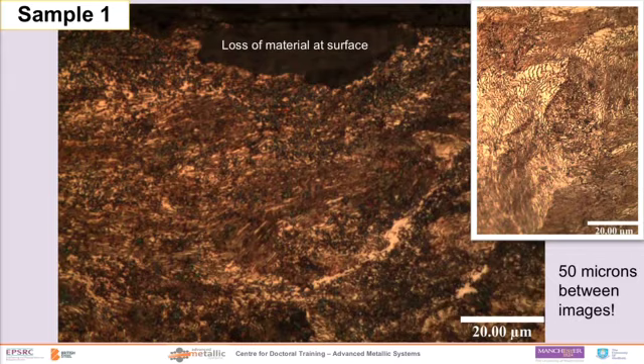So again, just to give you a bigger image of the type of martensite structure I'm typically finding at the surface of the rail. 50 microns below this image, you've then got what the structure should look like. You should be able to see the nice pearlite colonies. They should have nice clear grain boundaries, but clearly this isn't the case. And as well as being a very refined structure and a somewhat distorted structure, there's also a loss of material at the surface. This could possibly be due to white etching layer that's broken away during the sample preparation process.